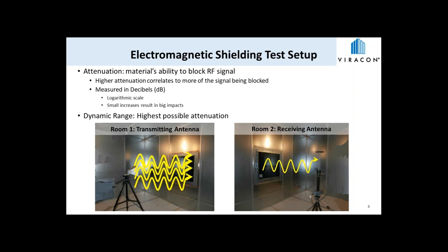So the electromagnetic shielding test consists of two metal enclosed rooms, as you can see in the pictures, connected by an interior wall with an opening in the middle of this wall called the aperture. In one room, on the left-hand side of the picture, there's a transmitting antenna, and in the other room, there's a receiving antenna. The transmitting antenna emits a known signal strength, and the receiving antenna collects any signal that it sees. A signal loss is calculated from the transmitting antenna to the receiving antenna with the aperture open, and then it's repeated with the opening covered with a metal plate. This is called the closed aperture.